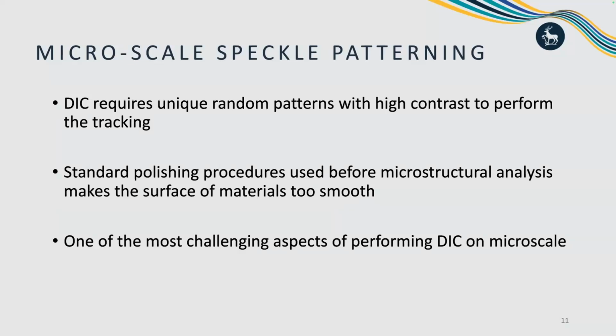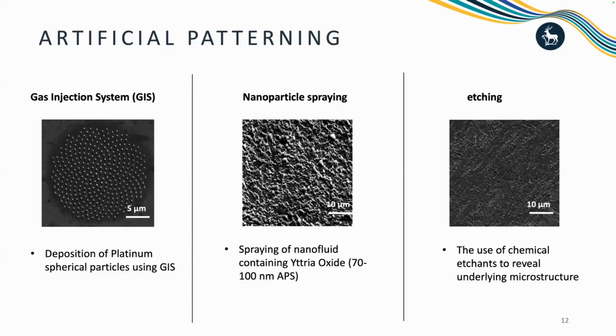For the DIC technique, with some materials the natural pattern, the natural features of the materials, is not very helpful for the DIC analysis because it's too smooth and there are no features to be tracked during the correlation. So we need to generate some artificial features to help increase the accuracy of the DIC analysis. Here are the general three methods: particle deposition using the GIS, nanoparticle spraying, and the last one is etching.